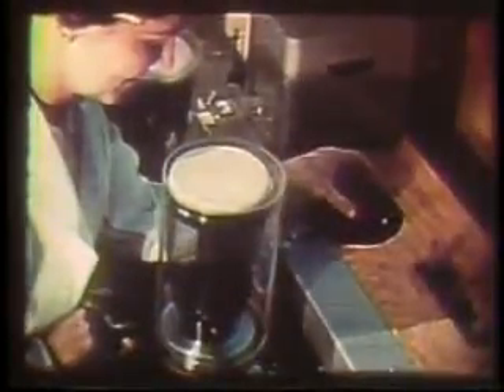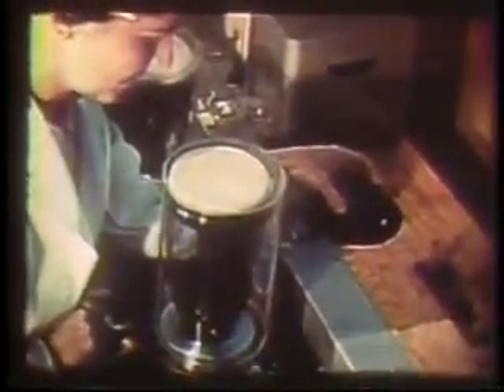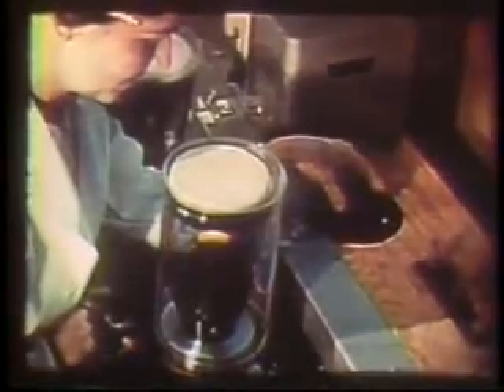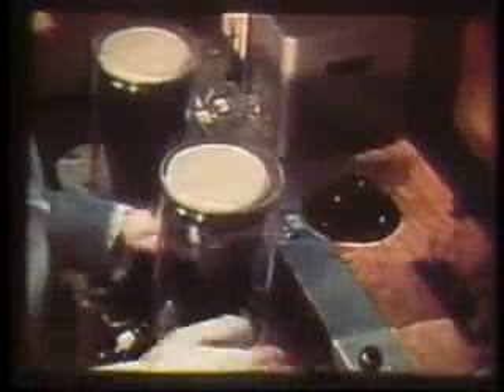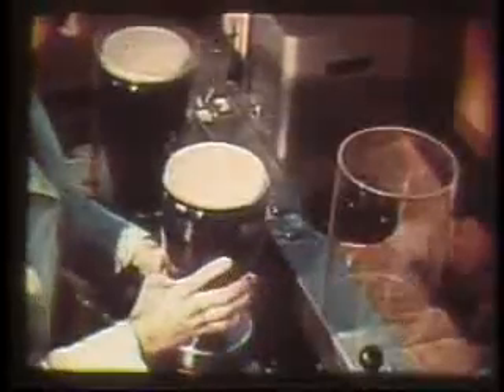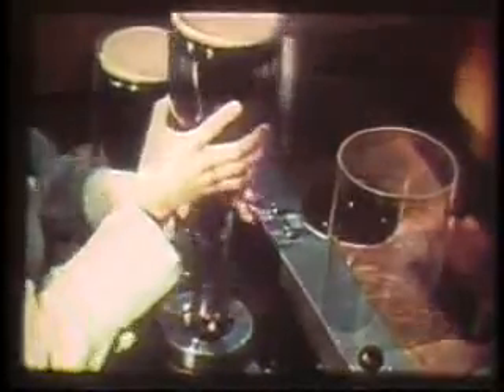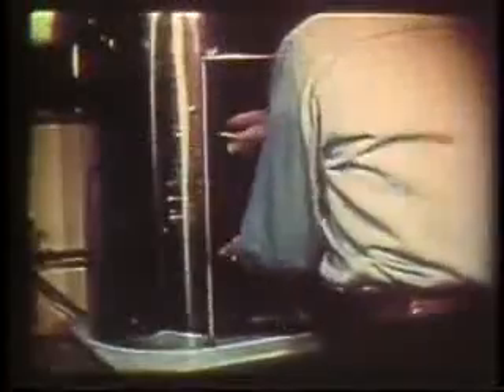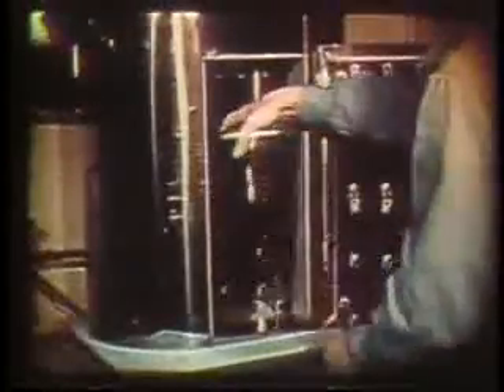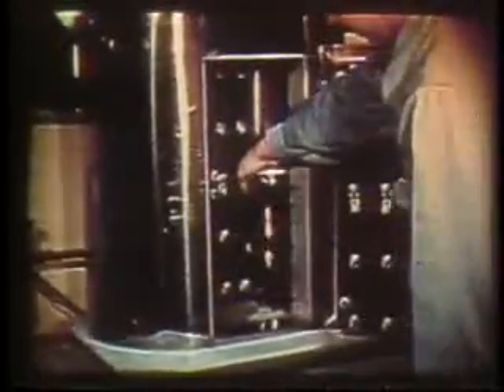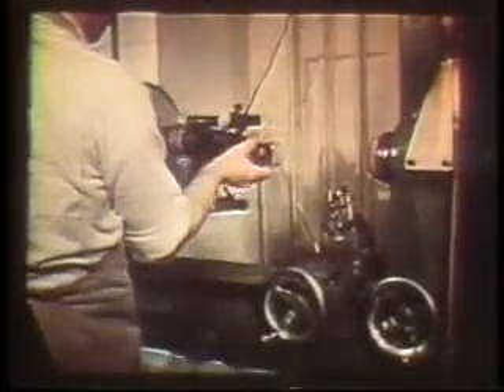After the tube is evacuated, the temperature of the heater is slowly increased until the aluminum is vaporized. The vapor immediately condenses onto the cool face of the tube. We have deposited a uniform aluminum film of a thickness of only a few microns. The tube envelope is given a final baking now at high temperature. This operation completely dries out all the remaining moisture, as well as burning out the lacquer separating the metallized film and the screen material.